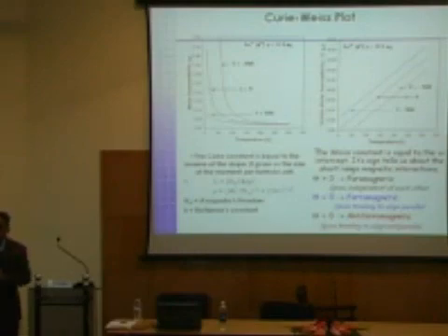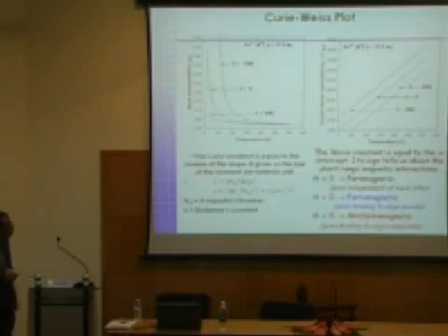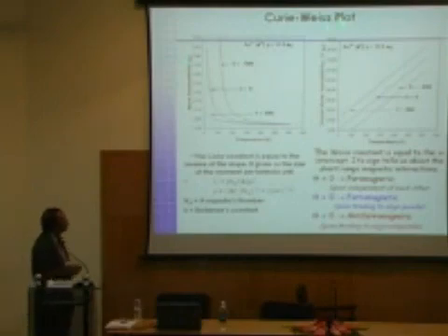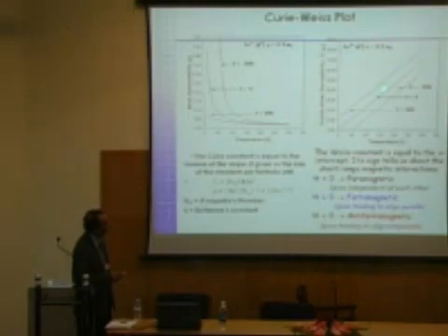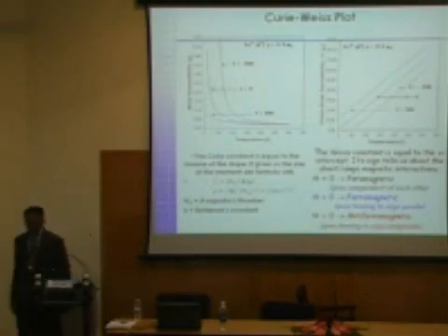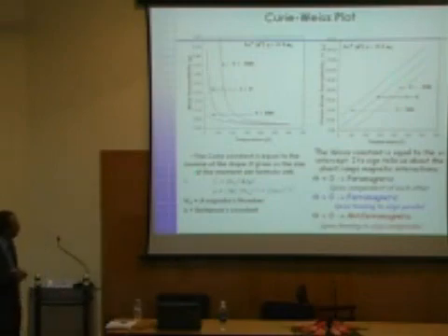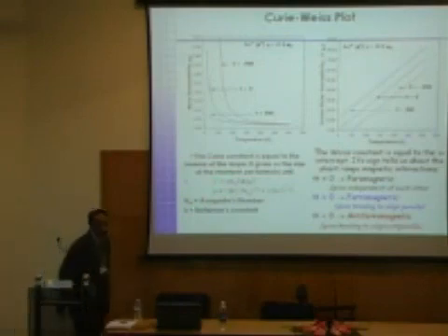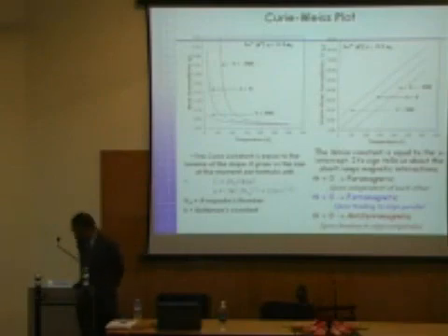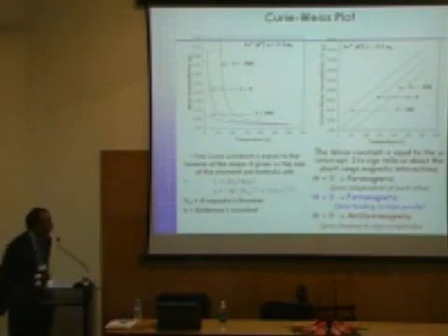So this is a very exciting way of changing the magnetic properties of solids. If you take the same data here and plot 1 over chi, which is the inverse molar magnetic susceptibility, as a function of temperature, you can see lines. If it is a paramagnetic substance, it will cut the 0 because there is no theta contribution here. But if it's antiferro or ferro, it's going to cut the x or y axis on the negative side. So this is the detail of the magnetic calculation. This is how you figure out from the experimental values how many unpaired electrons the system has.